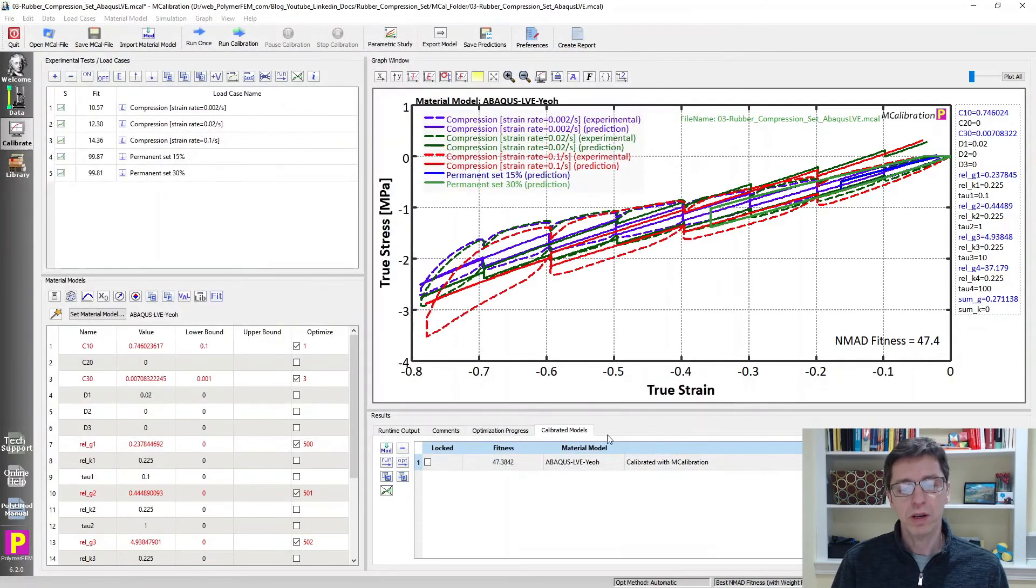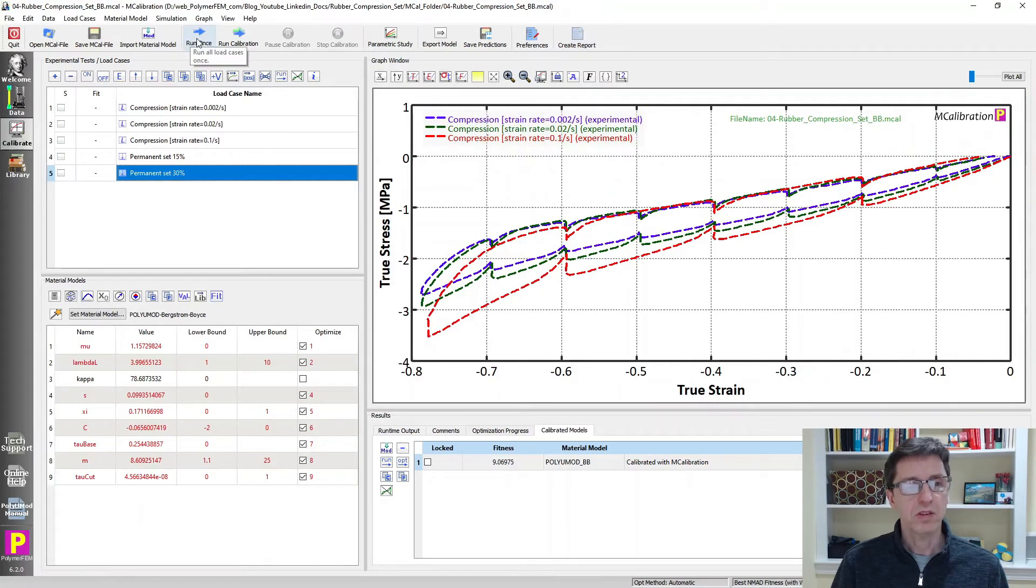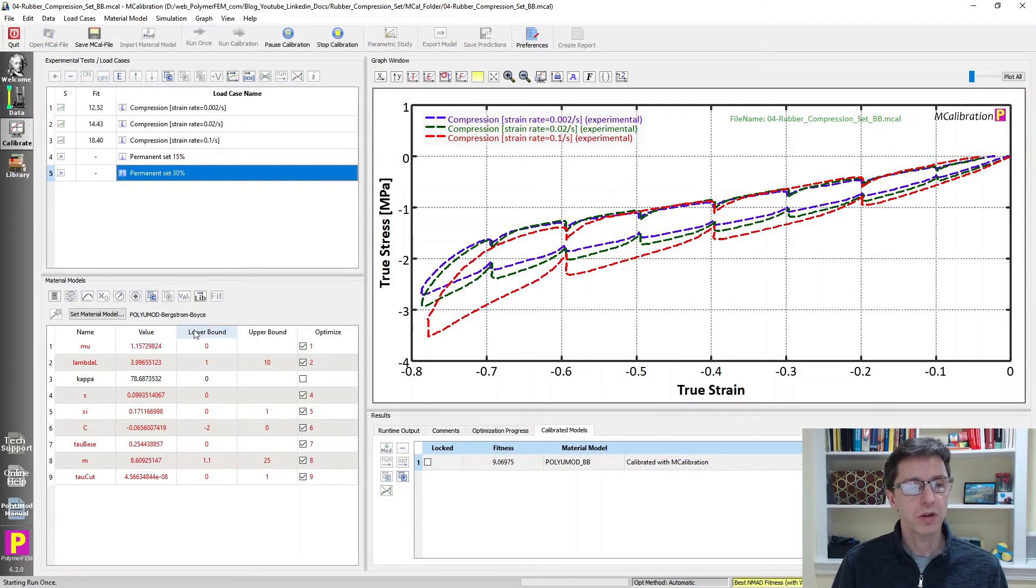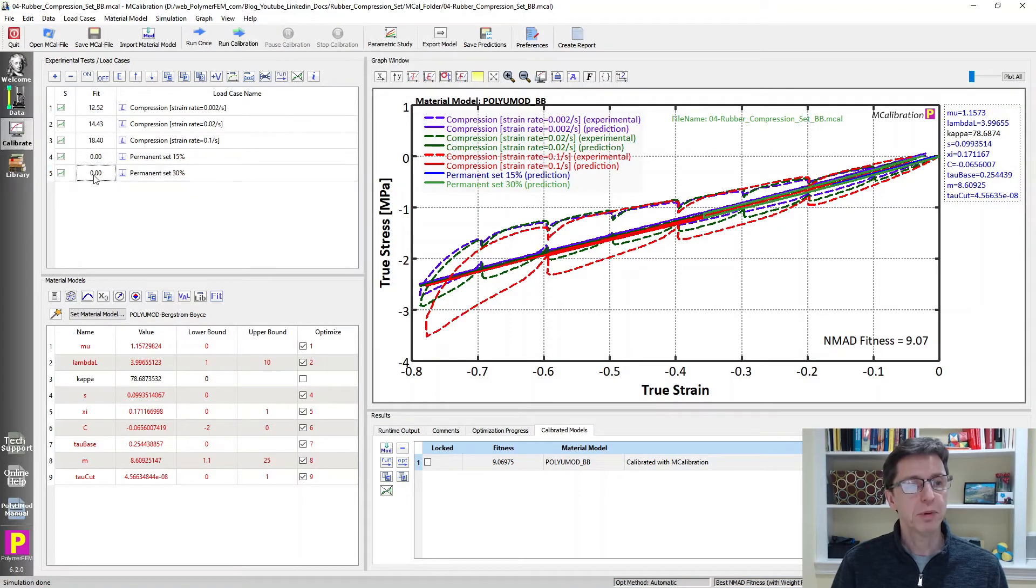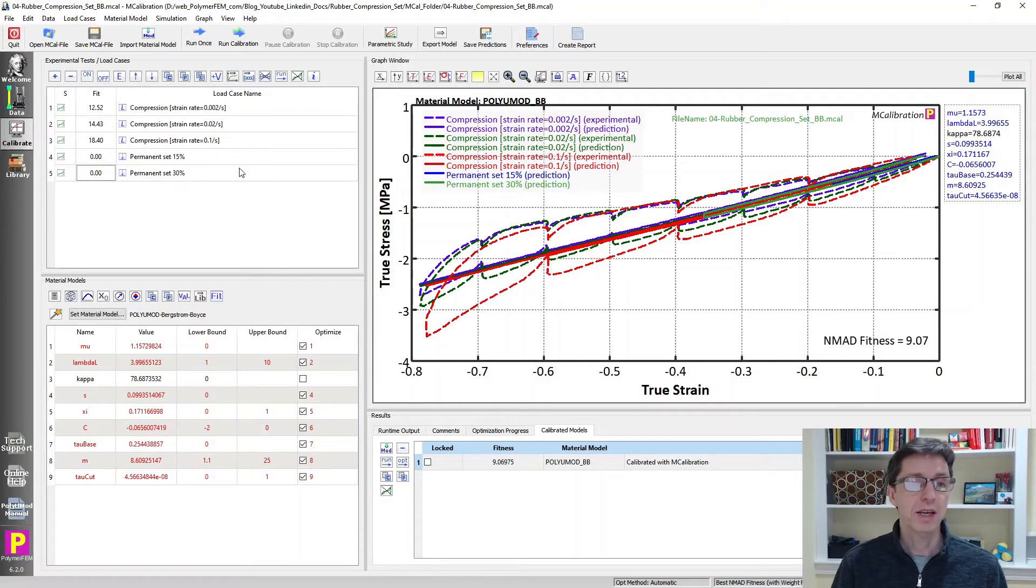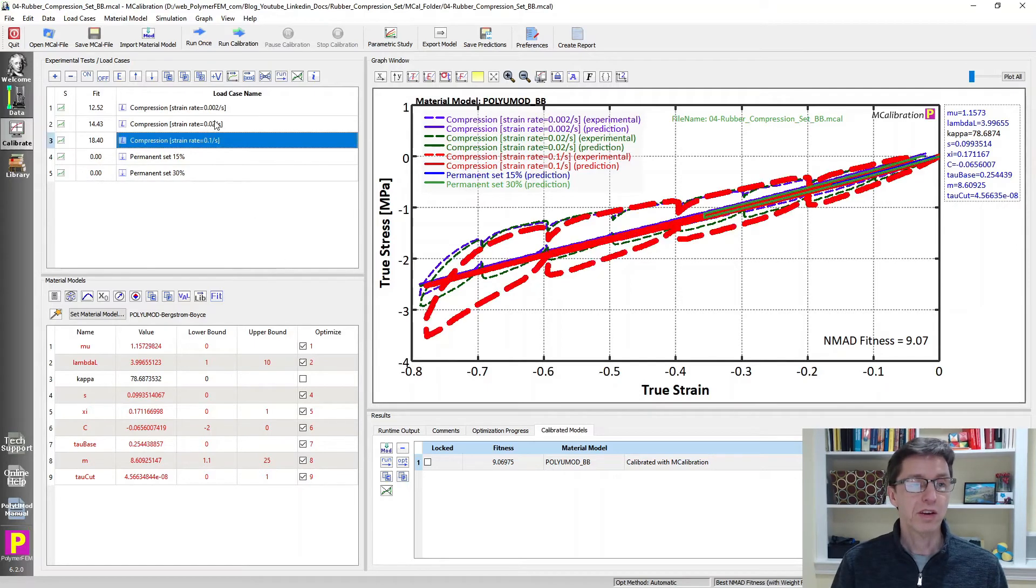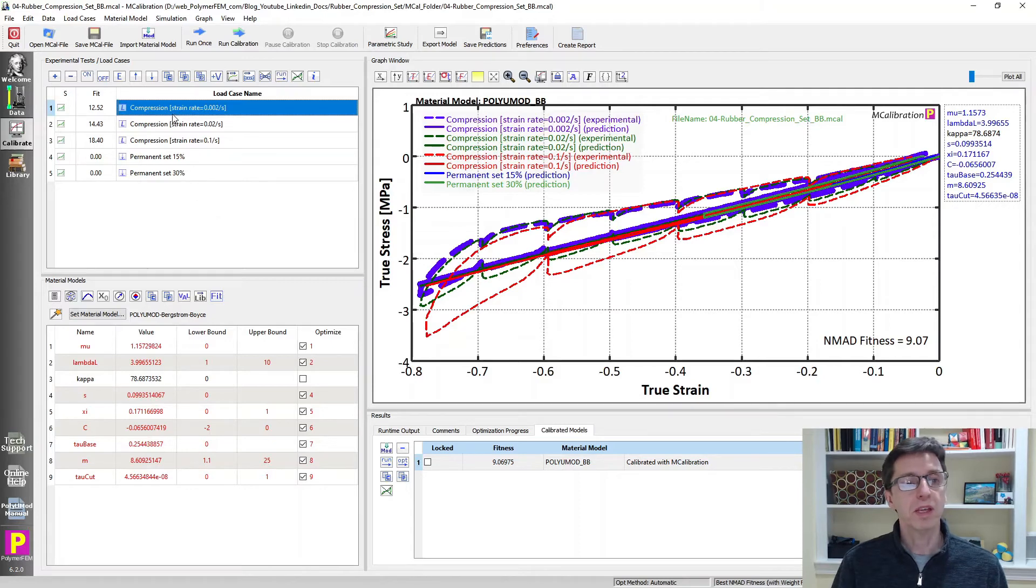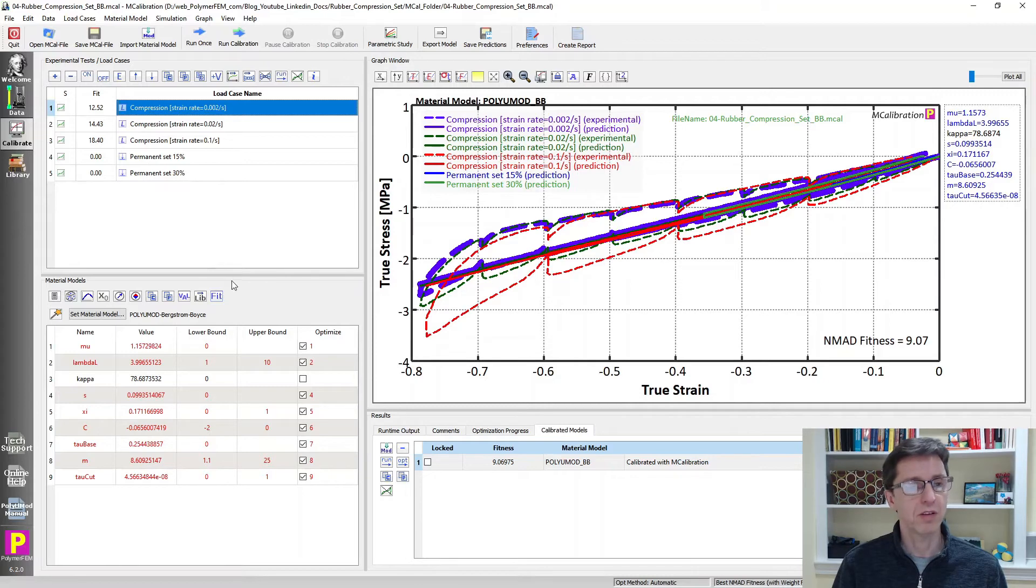So we've tried now a number of these that clearly don't work. Well, let's try something that perhaps is starting to be a little better. So the next one is the Bergstrom-Boyce model. This is the model I developed a number of years ago for rubber-like materials. Is this a better choice? Well, if you run this one, I just loaded up my saved calibration here to save time. We'll see that the Bergstrom-Boyce model can have predictions of permanent set that are close to zero. There is perfect prediction of permanent set, but unfortunately you sacrifice the viscoelastic response if you do that. You can also do the opposite. You can get very good fit to the compression data, but then you don't get the permanent set. So the classical Bergstrom-Boyce model can't do both in this case. So it's a little bit of a problem there.